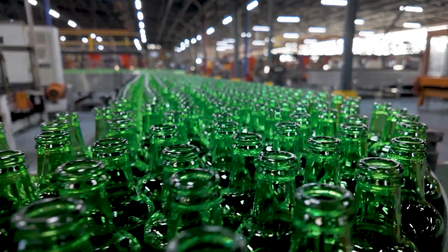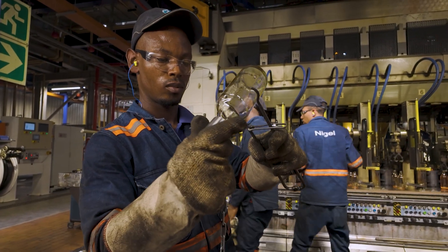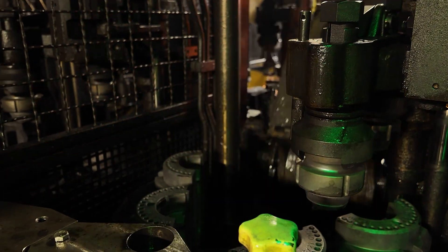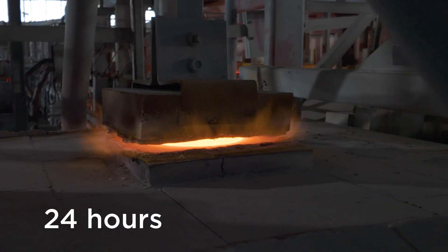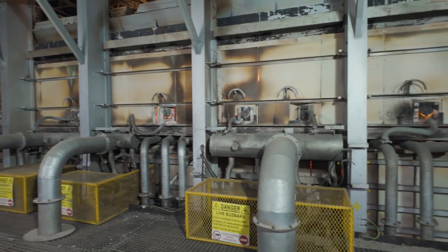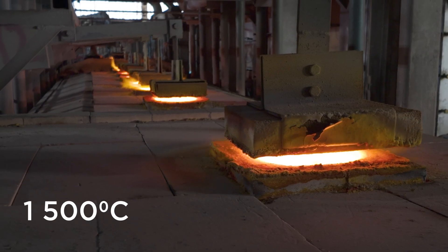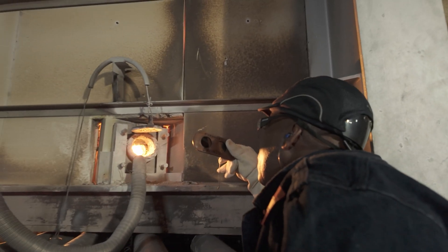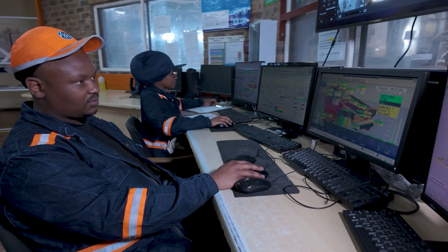Arda Glass Packaging uses leading-edge technology to ensure that the mixed material or batches delivered to our furnaces meet our stringent quality standards. It takes around 24 hours for a batch of raw materials to be converted into molten glass. Batches are continuously fed into the furnace, which operates at approximately 1,500 degrees Celsius. From the furnace, the molten glass makes its way to the refiner area, where it is cooled to approximately 1,200 degrees Celsius.